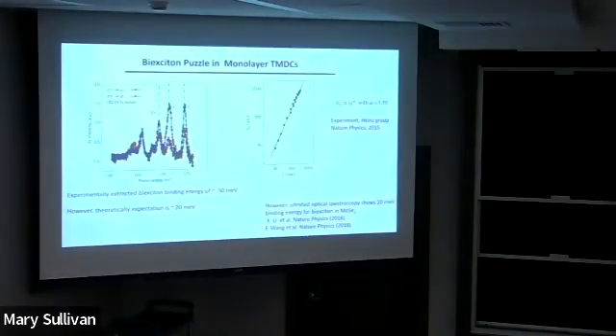One natural question to ask, like in gallium arsenide, is what's the biexciton? Understanding biexciton is extremely important to understand nonlinear properties, especially for lasing of these materials. As early as 2017, Tony Heinz's group was able to show the power dependence of PL, showing that one additional peak, which they call XX1, has a nonlinear, superlinear power dependence for biexciton, because the recombination rate is proportional to n squared.